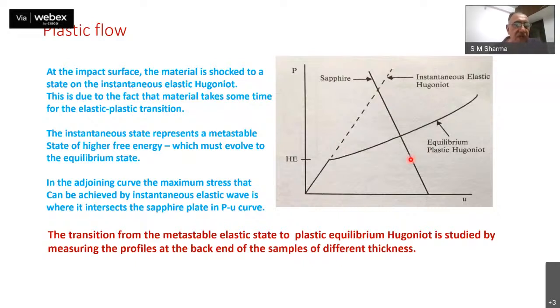Let me rephrase. At the impact surface, the material is shocked to a state on the instantaneous elastic Hugoniot. This is due to the fact that the material takes some time for the elastic-plastic transition. The instantaneous state represents obviously a metastable state, and therefore is a state of higher energy, and it must evolve to the equilibrium.